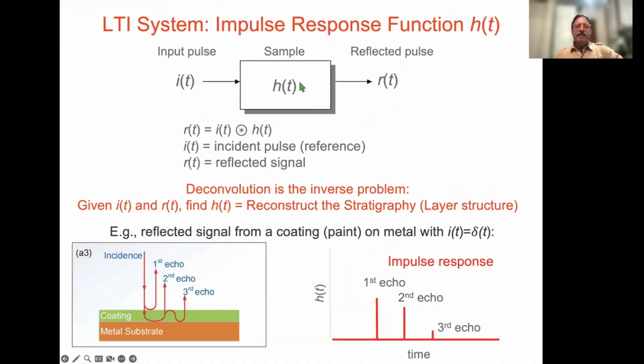The problem can be viewed as a linear time invariant system. So we know the pulse we send in, we measure it. We know the signal we get out, we measure it. But the question is, how do we figure out what the impulse response is? Because that tells us about the sample. So the problem here is one of deconvolution. Deconvolution is an inverse problem. It can be a very hard problem because the easiest way to do this, one would hope, is to Fourier transform, use the convolution theorem, and recover the transfer function. But because of noise and other issues, that usually doesn't work. So we usually use time domain techniques.